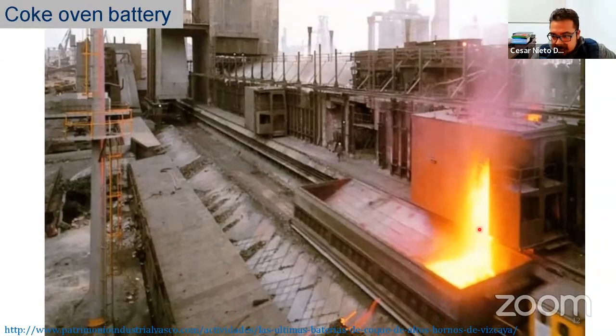And this is essentially the coke that is being pushed out of the battery, and because it's at 1000 Celsius, at contact with the air in the atmosphere, it just gets ignited. I visited two or three coke companies in the US and one in Mexico, and what they do is they just apply water to avoid the consumption of the coke.